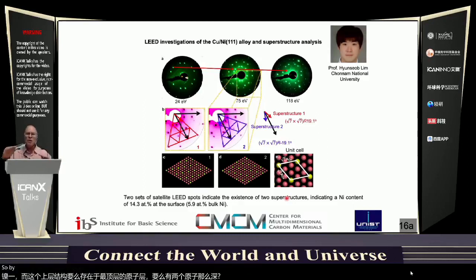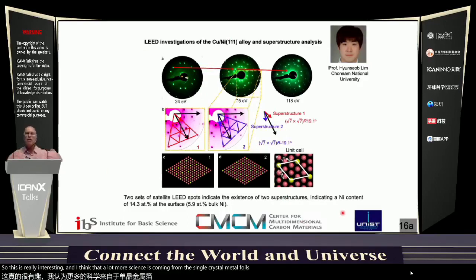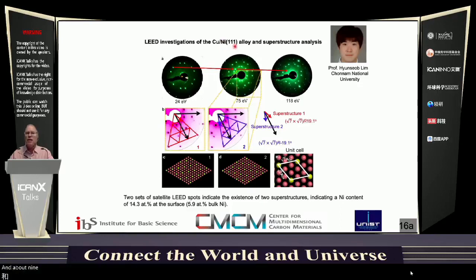So by lowering the kinetic energy of the incident electron beam, it's possible to interrogate just the very surface and not deeper into the material. So this is really interesting. And I think that a lot more science is coming from these single crystal metal foils by mixing in other elements, because we find this superstructure present when we are working at concentrations anywhere between 1.3 and about 9.8 atomic percent. We didn't exhaustively research that, but that superstructure forms with a relatively high percentage of nickel at the surface, even when the bulk nickel is at a much lower content.